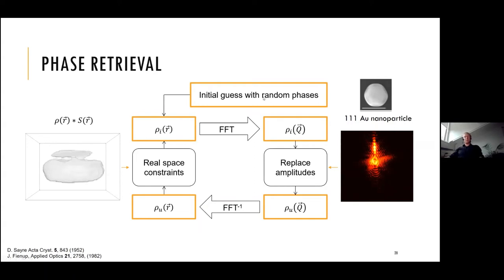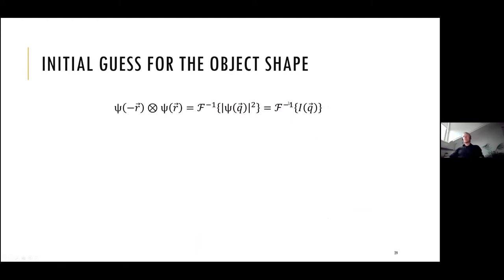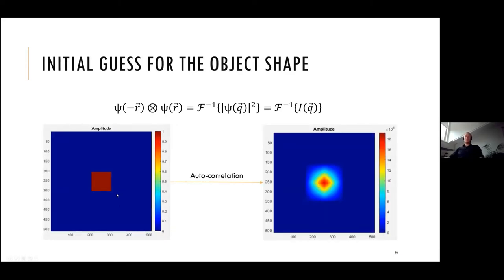And I actually want to make a small remark on how you can guess the shape of the object right away, knowing only the intensity. Just a small hint. You know that the scattering intensity from the object is basically an autocorrelation of the wave field coming out of the object. So you can exploit this fact and calculate the inverse Fourier transform of your measured intensity, and then you get the object, whose amplitude is twice as large in each dimension, but it's already a very good approximation to the shape and size of your particle. So you can use this as an initial guess, and you will be very close in most of the cases.